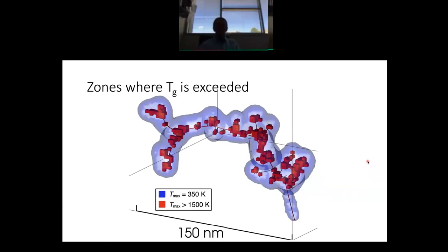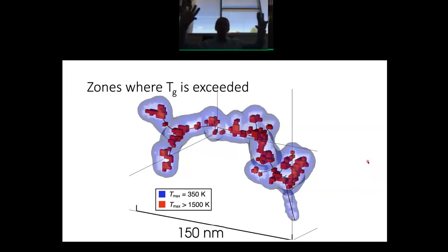One of the first things that we could do is figure out the locations where the temperature exceeded the glass transition temperature. All the red boxes here show you the locations where the glass transition temperature was exceeded. Those are the molten regions, the liquid regions of the thermal spikes. And then surrounding them, the temperature rose to 350 Kelvin, above the initial ambient temperature. So it's heated up, but it hasn't melted.